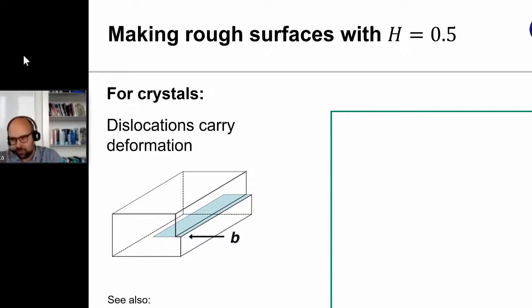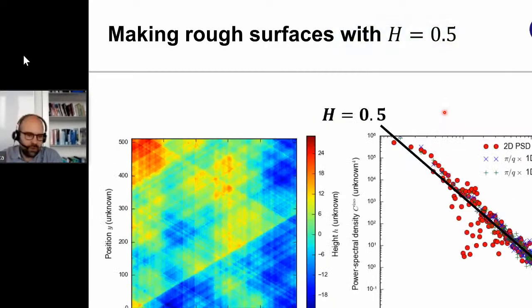So let's make a rough surface on this little square that you see on the right. I'm just throwing onto the surface a random step. So when I come from here, when you see my pointer, I'm moving towards the step, then I would move up by a little bit, by a Burgers vector, when I move over the step. And now we do this randomly on the surface. And when we do this randomly, we get a surface that looks like this. Here, the directions are now simply chosen from the slip directions on an FCC 111 surface.